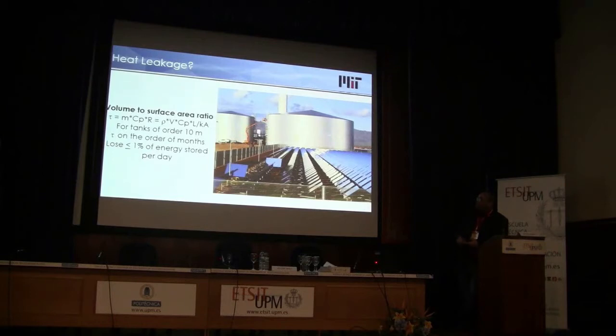Today they operate molten salt plants and molten salt tanks with less than about 1% of the energy stored lost per day. This is an acceptable regime to be in, and so we're interested in doing essentially the same thing. When you go as hot as we're interested in, it requires some different types of insulation, which are not negligible cost-wise. But one of the key things is also, once you make it really large, the time constant, the time it takes for it to cool down, also scales with that volume to surface area ratio, and so that gets longer and longer. Typically these tanks have time constants on the order of months, so they can sit idle without doing anything for multiple months without freezing. So this is another important thing.